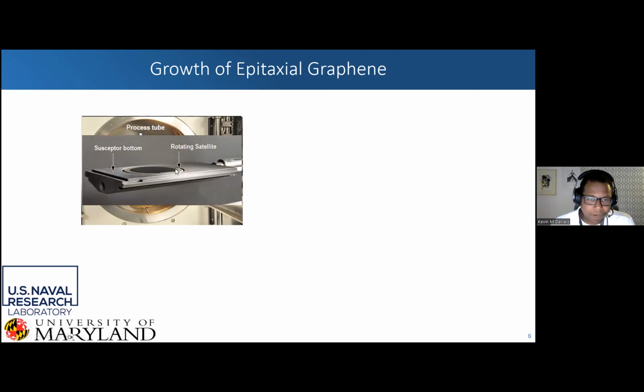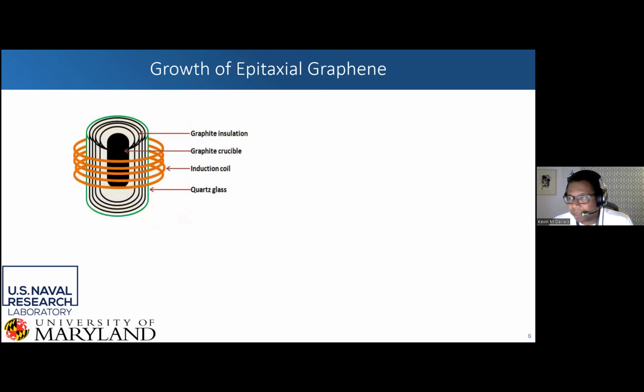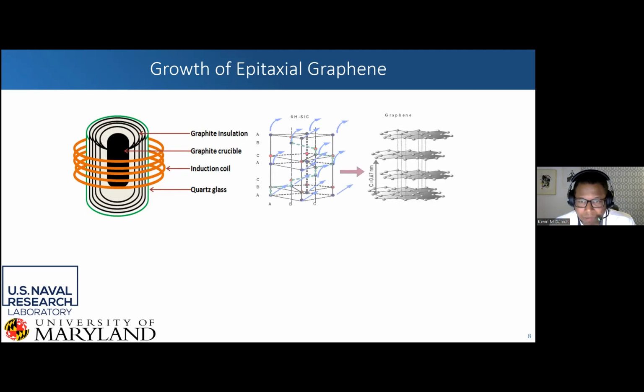And the reason why everything is made of graphite is because of our heating. So we do inductive heating with the system to induce eddy currents into our graphite in order to heat it up. And we get pretty high temperature uniformity, around plus or minus 1 to 2 degrees C across an entire 4-inch wafer. So it is extremely tight temperature tolerances because of how we're really growing our material, right? It's entirely through thermal decomposition. Silicon and carbon have different vapor pressures, so the silicon desorbs off, the carbon stays behind, restructuring itself into really nice single crystal graphene.